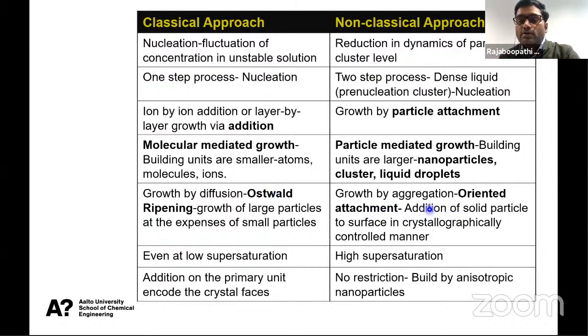Here, it is a kind of oriented attachment, a crystallographically oriented attachment, to explain the further growth. In a classical approach, even at a low supersaturation, we can get crystals, but for the non-classical approach, we need high supersaturation. So based on the stability, it will produce a hierarchical structure, or it will produce mesocrystals, or it will produce oriented attachment. Everything is based on how you are controlling the basic building unit nanoparticles.